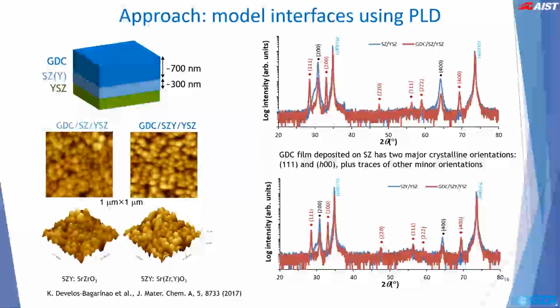Towards a better understanding of the role of interfaces in general, as well as to elucidate the influence of secondary phases on oxide ion transport, one approach we have adopted is to use model systems based on thin film structures. To understand the effect of strontium zirconate in particular, we prepared heterostructures where the strontium zirconate or yttrium-doped strontium zirconate layers are sandwiched in between GDC and YSZ, similar to the commonly observed structures of sintered SOFC cells.